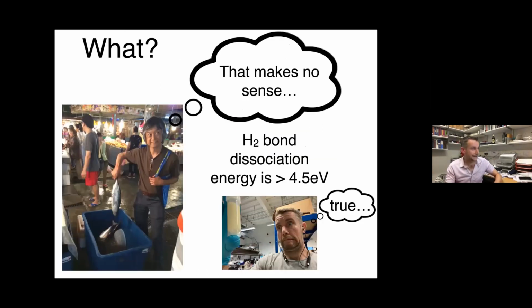Because this doesn't make any sense, okay? Hydrogen has a dissociation energy of 4.5 eV. So if you take a diamond and you heat it to 500 degrees in hydrogen, nothing should happen, right? So this started a bit of a discussion. I did actually mention in the paper that this didn't make a lot of sense, but I just said it's something to do with sp2, which is not a very satisfying answer.